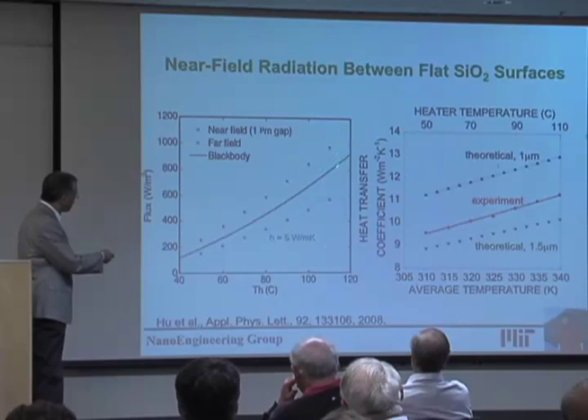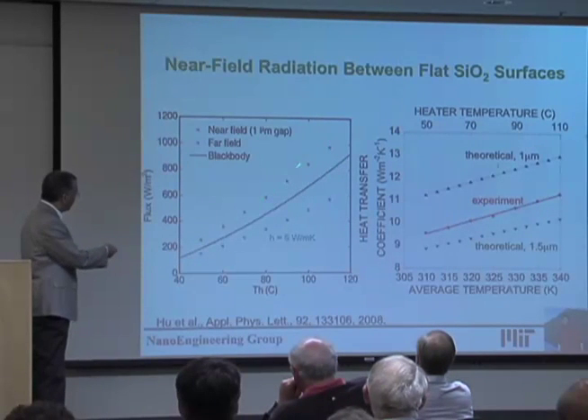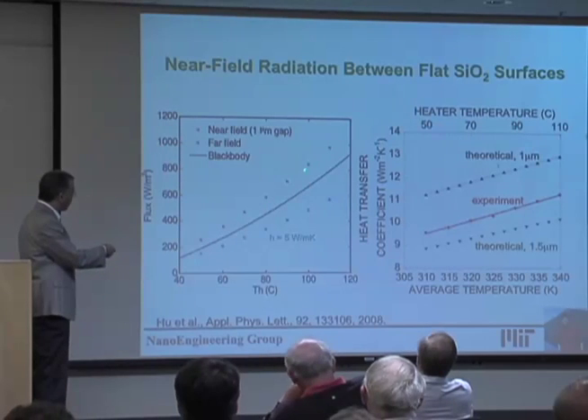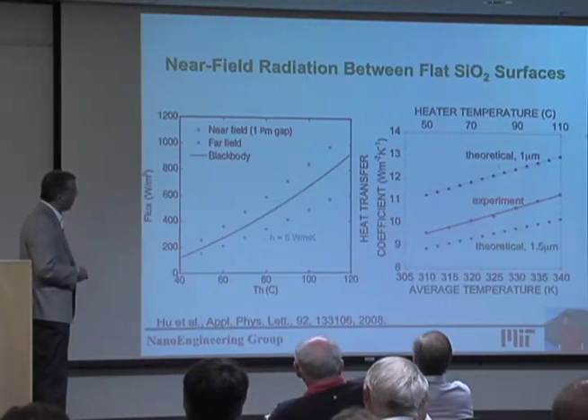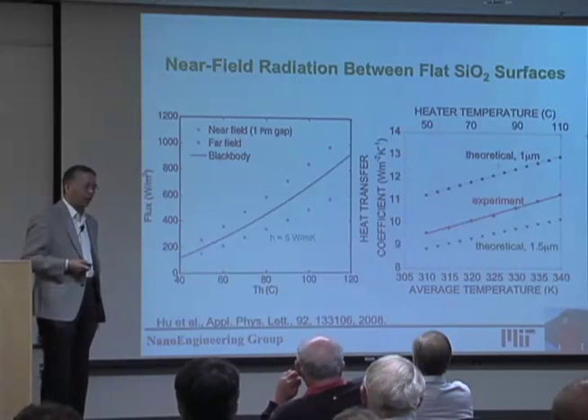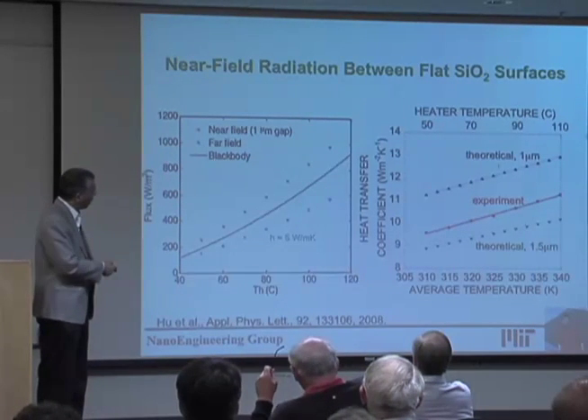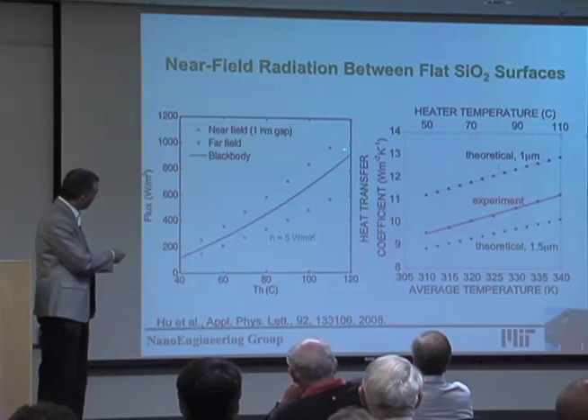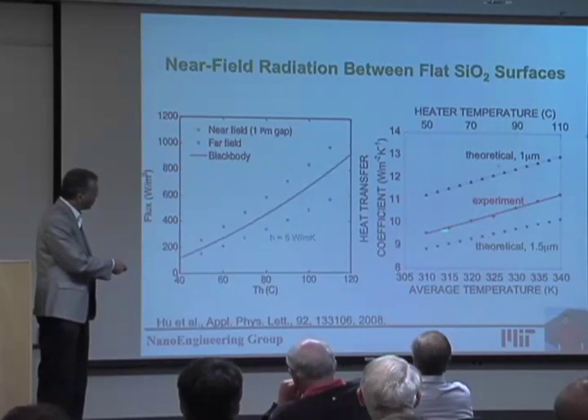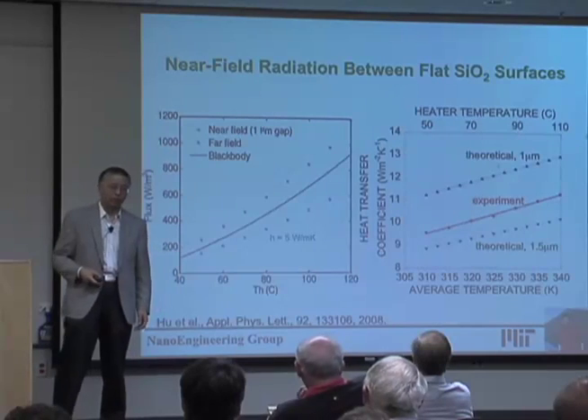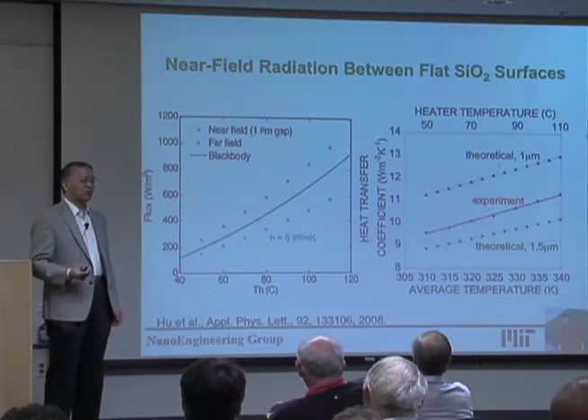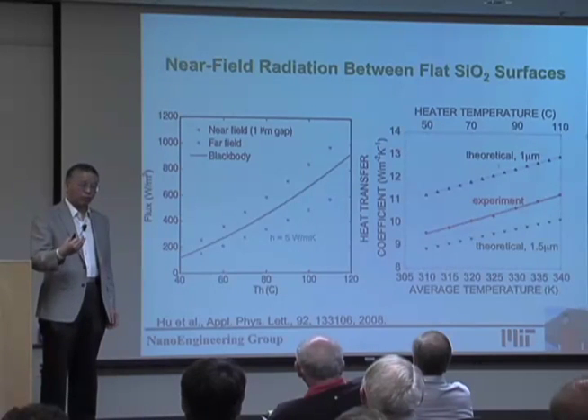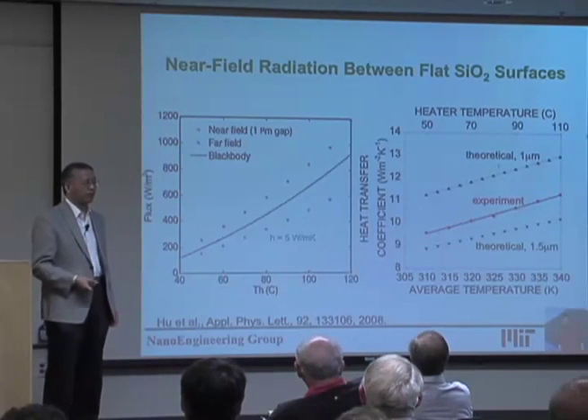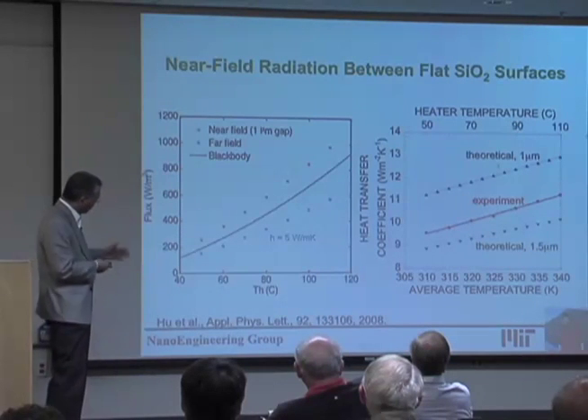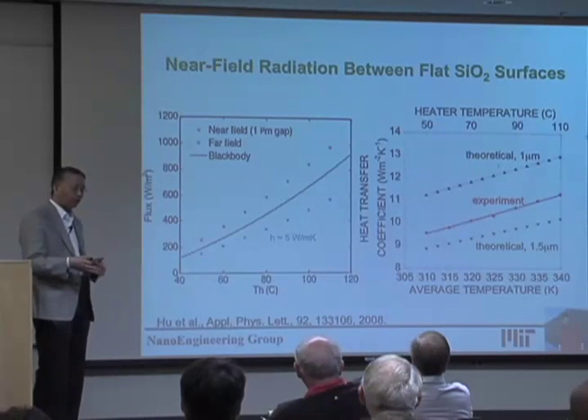Here is blackbody radiation, and here is when the two surfaces are of the order of a micron, and here are in the far field, and you can see that we can go beyond the blackbody radiation. But when we compare with theory, nominally this sphere is 1 micron, and the experiment falls in between 1 micron and 1.5 micron. The reason was the sphere is not a uniform diameter, and in spacing control it's the larger diameter that determines the spacing. But when we tried to push this to smaller spacing, it didn't work.